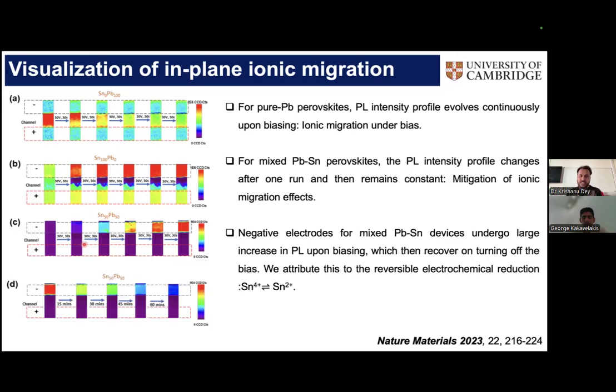But there's an interesting thing that we see, that if you look at the negative electrode, when we are biasing the negative electrode for the tin-based perovskites, they tend to increase in intensity, which is not seen in the lead-based perovskites. So that was very interesting. So negative electrode has a lot of electrons, of course. So something is happening as you are biasing them, and we wanted to see whether this is reversible, and then we left them under the non-biased condition, and if we just let them relax and then we track the PL again, we see that they increase first, and then if you leave them unbiased, they go back to lower PL again.